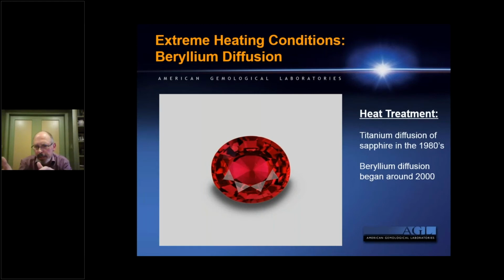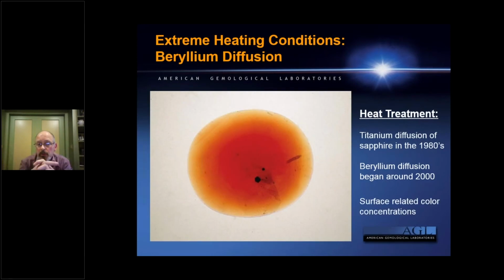Beryllium diffusion, which began around 2000, is a different scenario because you're actually able to diffuse beryllium much deeper into the stone. And so you can even diffuse beryllium throughout the stone. So when you put a beryllium diffused ruby into immersion and over a diffused light source, what you want to be looking for is something like what you see here, which is actually a ring of yellow to orange color, which is also surface conformal. It's following the outline of the stone, but it's not a patchwork. It's more a ring of color.